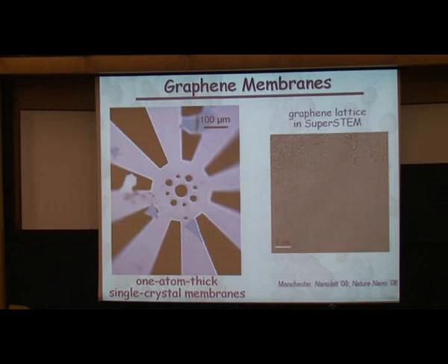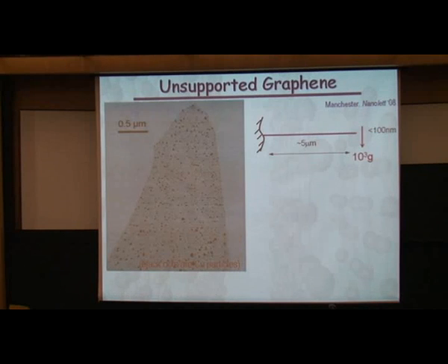Initially it was just to see this material. You can see its crystal lattice quite clearly. The electron goes through the middle of the ring, the benzene ring. When it hits the bond, it's slightly reflected. It's extremely weak contrast, essentially. If you put any other foreign atom on top of this, you can distinguish it reasonably easily. This is the case of oxygen or silicon, but you can distinguish even hydrogen or even a foreign carbon atom on top of this.